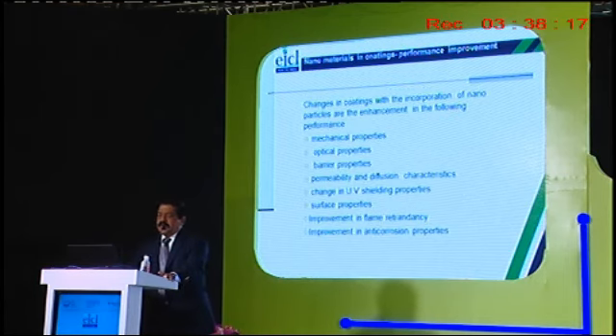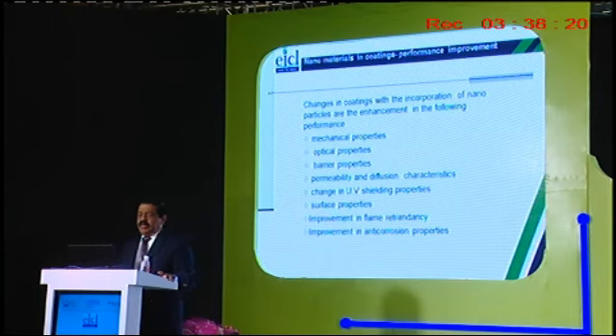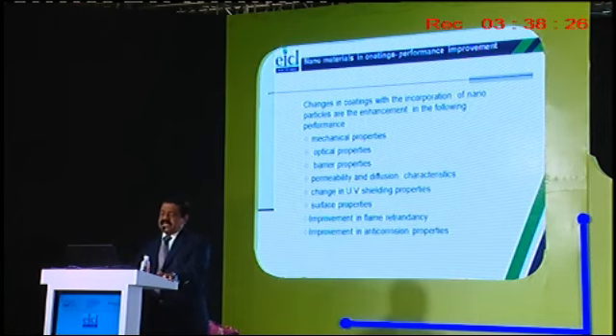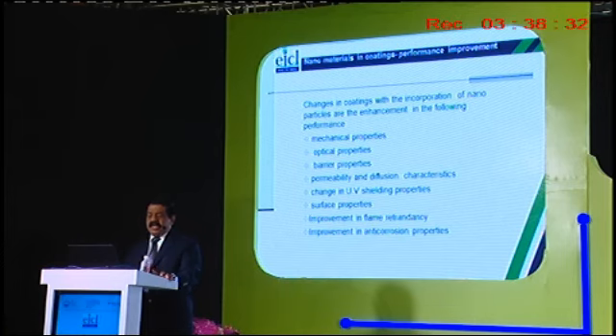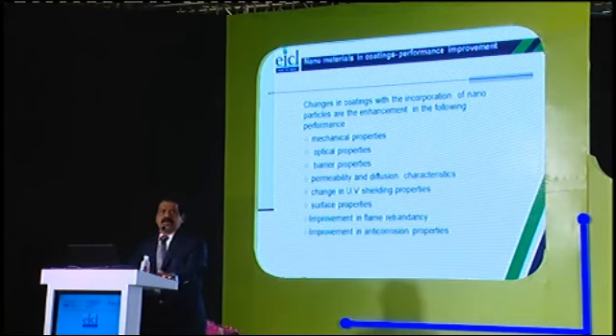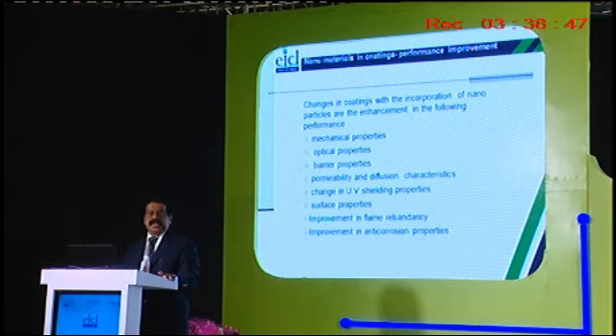Now, if you see how the performance changes when using nanomaterials, the changes in the coating with the incorporation of nanoparticles are the enhancement of the following properties: mechanical property, optical property, barrier property, permeability and diffusion character, change in UV shielding property, surface property, improvement in flame retardancy, and improvement in the anti-corrosive property. So a lot of properties can be enhanced in the coating, or your coating life can be increased by incorporating the nanomaterials.